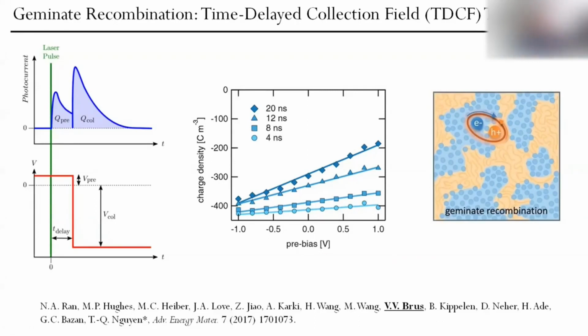So if we have a bad combination of donor and acceptor materials, this can be maybe 10% or 20%. So only 20% of all photogenerated excitons will be split into free charge carriers. And that means 80% of potential free charge carriers are lost just because we couldn't split photogenerated excitons. That is very bad. That's why the highest performance devices nowadays, the best blends of donor and acceptor, possess this geminate prefactor of about 95% and higher. Some reach even unity, like 100%.